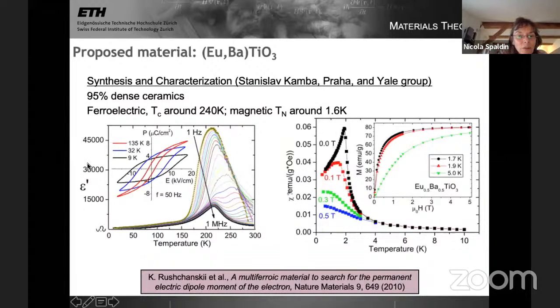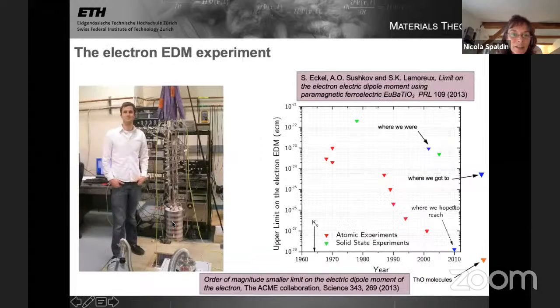So here's the dielectric response as a function of temperature. And this cusp here is indicating the ferroelectric phase transition. And here we see the polarization as a function of electric field at different temperatures. And here's the magnetic permeability as a function of temperature. Remember, it had to have not ordered by liquid helium temperature, which it doesn't. So we wrote a nice paper about designing the material, and then our colleagues took it back to Yale to try to measure the electron electric dipole moment.